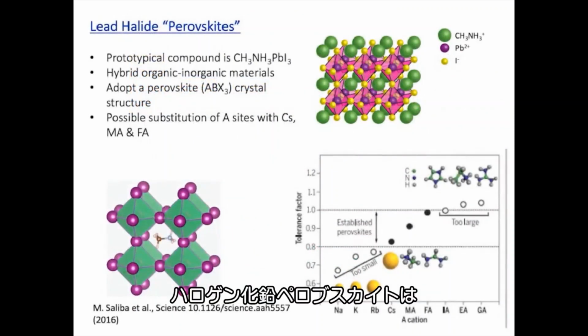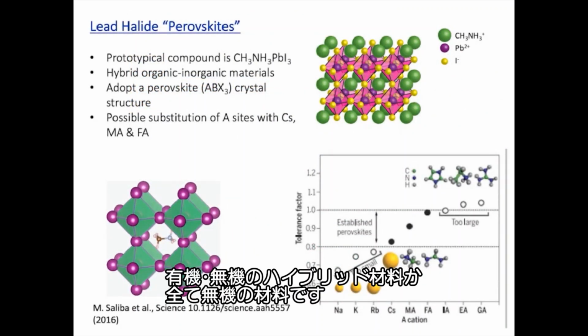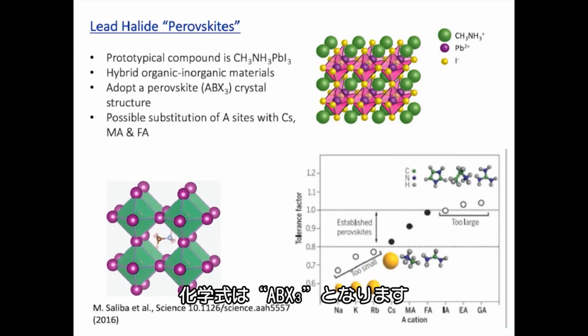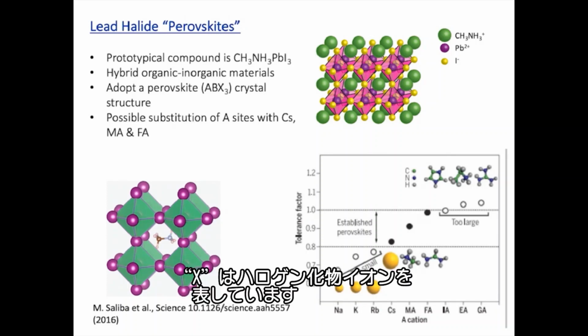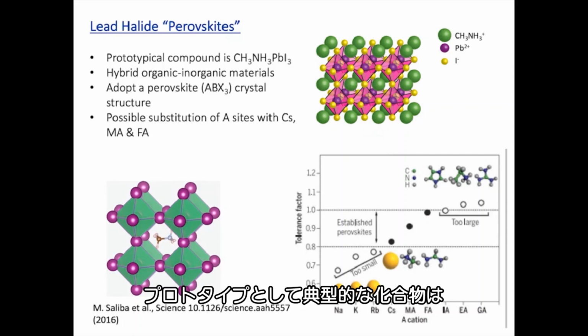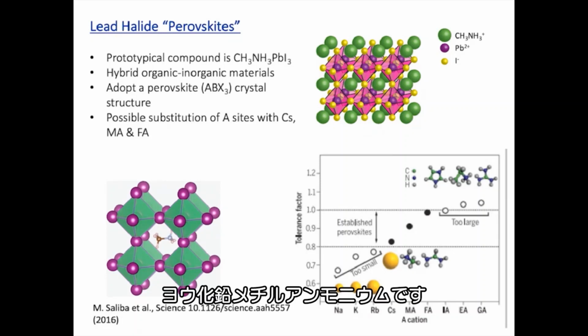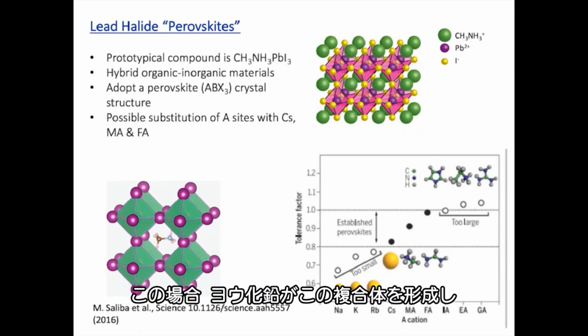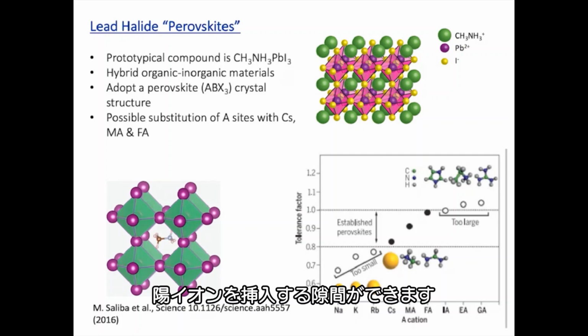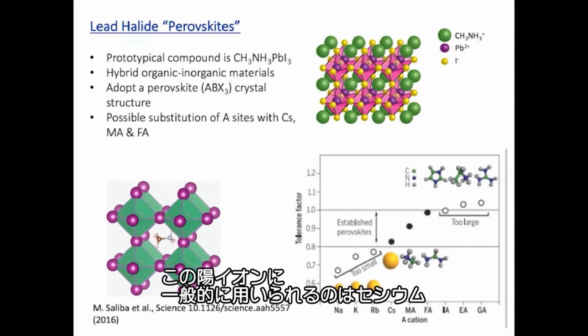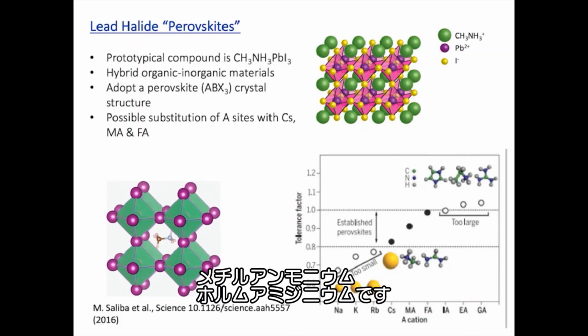Lead halide perovskites are essentially hybrid organic-inorganic, or also all inorganic materials, where they have a formula ABX3, where X refers to halide ions. A typical prototype compound is methyl ammonium lead iodide, and in this case you can see here the lead iodide forms this complex and generates this cavity in which a cation gets inserted, and this cation is typically cesium, methyl ammonium, or formamidinium.